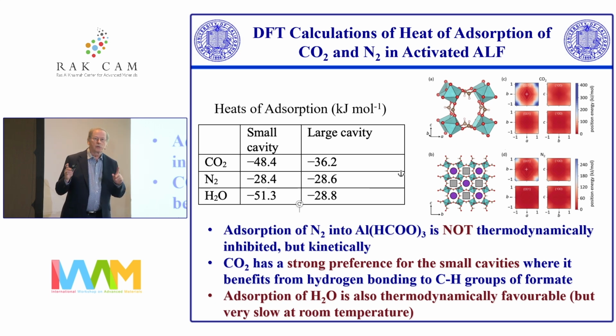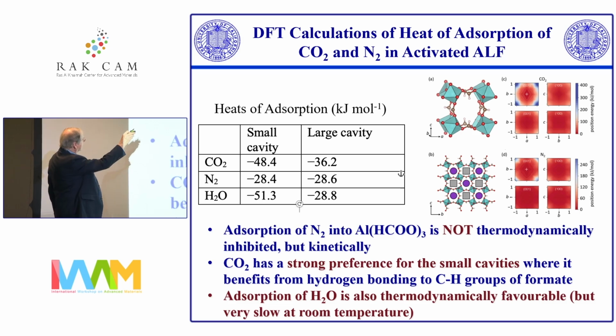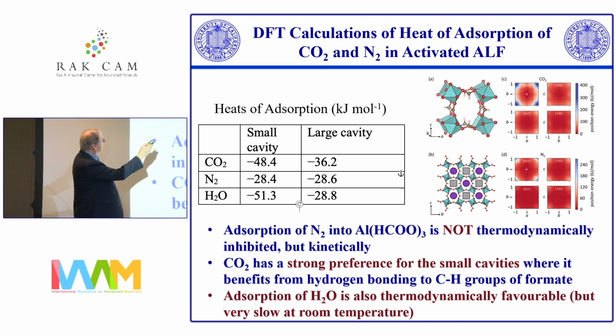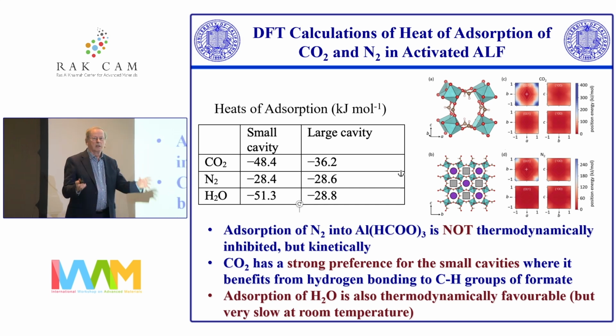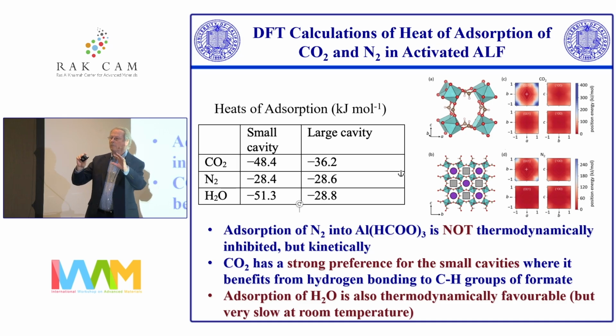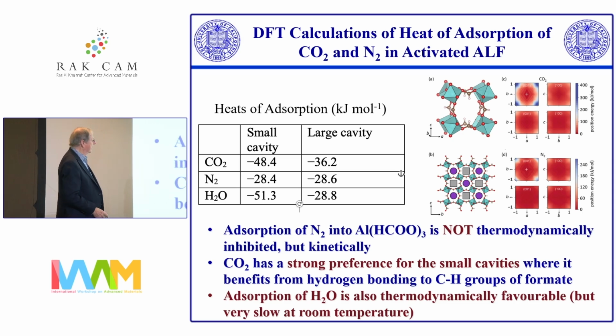In principle, nitrogen should go in. It fits in the cavity, and in fact, the heat of adsorption of nitrogen is nearly 30 kilojoules per mole. Water should go in. It doesn't go in very easily. We've done water adsorption isotherms. Room temperature, it doesn't go in easily. But you see in the two different types of cavities, the calculated heats of adsorption of CO2, 48 in the small cavity and 36 in the larger cavity. There are only sort of 25% of the cavities that are large, so most of the CO2 goes into the smaller cavity with its better heat of adsorption.